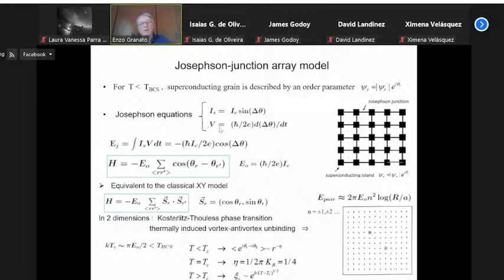If there is a change in phase as a function of time, then a voltage develops. The energy associated with a particular junction can be obtained by integrating the current times the voltage, and because the current has a sinusoidal relation, the energy associated with a single junction then has a cosine of the phase difference. The amplitude is proportional to the critical current of the junction, and there is a minus sign here. So the minus sign implies that the minimum energy for a junction is when the phases are the same. The energy contribution can be extended to the full array, and then the total Hamiltonian of the system is a sum of these cosines of phase difference, with the amplitude proportional to the critical current of the junction, and the minus sign means that the ground state is obtained by having the phase uniform in the whole system.